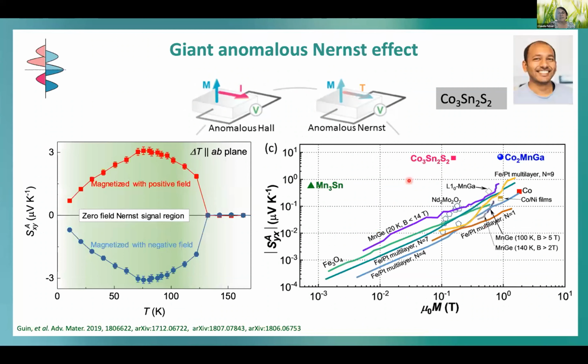The agreement between calculation and measurement is also very nice in the case of the Nernst effect. You see a large Nernst effect, and since the material is hard magnetic, you even see a Nernst effect at zero field, and you can switch the sign of the Nernst effect by switching the magnetization.